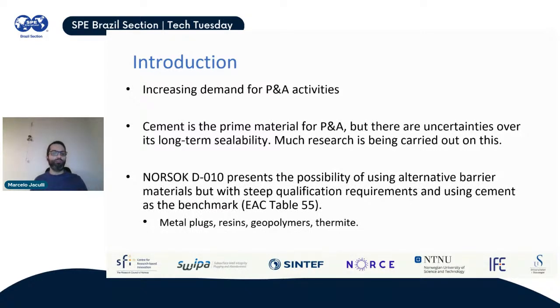The major problem here is that NORSOK D-010, which is the baseline for us here in Norway, and I believe is much followed in Brazil as well, has a table, Table 55 in the latest revision, with very steep qualification requirements for any alternative barrier material that is not cement. Of course, you need to use cement as the benchmark. So you need to prove that your technology is as good as or better than cement if you want to use it.